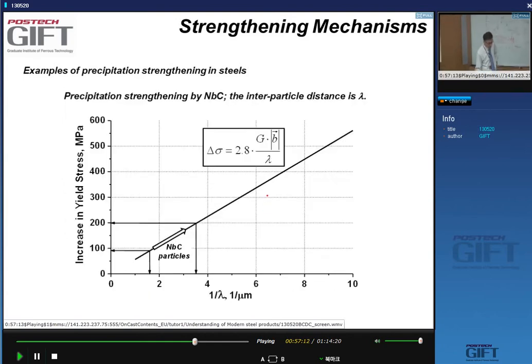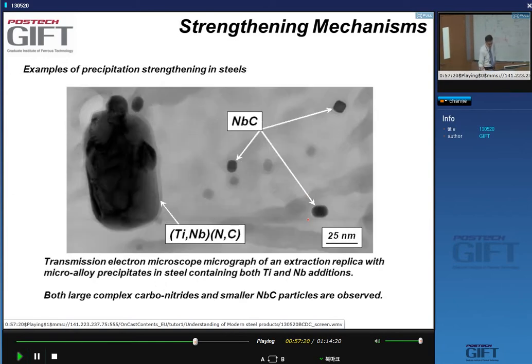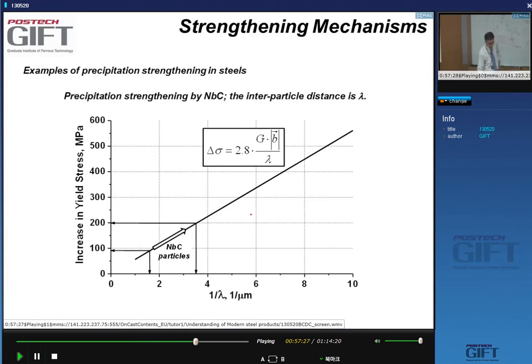So in general, if you have small niobium carbide precipitates, you can look at the main parameter that will influence the strength, which will be the volume fraction. And if you can change the density of niobium particles that are the same size, then the main parameter is the interparticle distance.